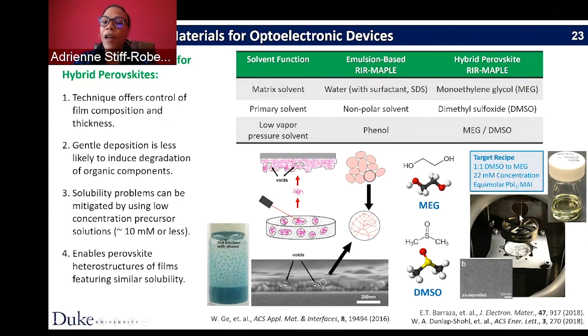In contrast, for the hybrid perovskites, we have solutions. And those solutions are frozen, and when we deposit the film, we're actually delivering the organic and inorganic precursors to the substrate, which then form this three-dimensional structure, this crystal structure, either during the deposition itself or with additional annealing to form the crystal. So this gives a lot of benefits for these hybrid perovskites. One, we can control the film composition and the thickness in a vapor-based process, which can be difficult to control because the organic molecule is very sensitive to any type of thermal evaporation. It's a gentle deposition technique, so you're not going to damage that organic material.